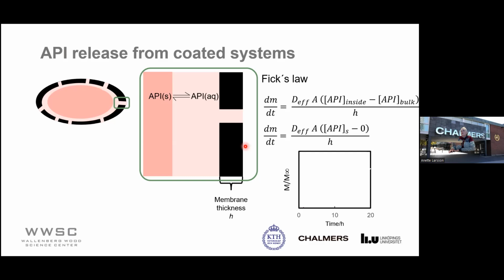So if we now take a look into this one, we can integrate, and here we plot the fraction of released drug. So this is at the time t, and then here we have it at infinity. So when everything is released, as a function of time, this is what we call a release curve. So what happens first is that we have a lag time here. That means that it takes time for the water to penetrate in and dissolve the pore, and also dissolve the drug, before the drug is released. So that is what we call a lag time.